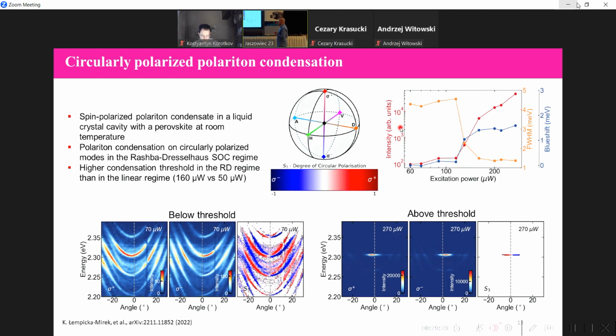There is also a higher condensation threshold when we need condensation at the Rashba-Dresselhaus regime, compared to just condensation in the linear regime - almost three times higher. One can think that this is only a disadvantage of this system, that you need more power to obtain these condensates. But it can also be useful.